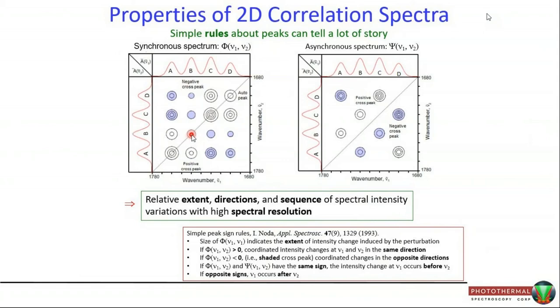If the direction of these two band pair, A and B, for example, are in the same direction, there will be a positive cross peak off diagonal position. On the other hand, A and C, if they are changing in a direction opposite to each other, that means one is increasing while the other is decreasing, there will be a negative cross peak indicated by the blue shading. This is a synchronous spectrum property.